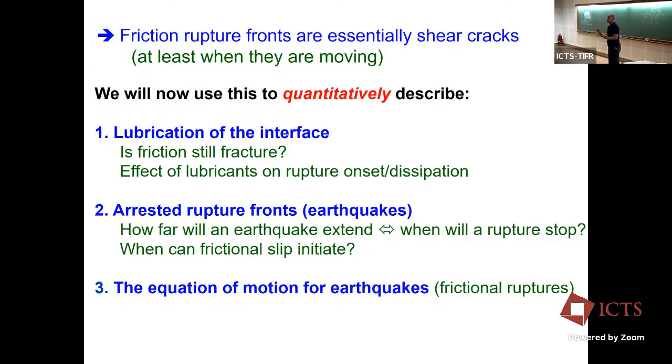But actually, I'll give you the easy answer. LEFM, linear elastic fracture mechanics, works, so apparently the assumptions are justified. If, on the other hand, we didn't go to the trouble of getting rid of the waviness of the plates, then we would be talking about maybe jumping from one contact to another contact. Three points could hold up the interface. Not really, but that's the idea. So here we really are talking about a continuum.